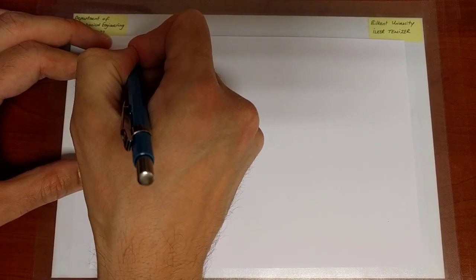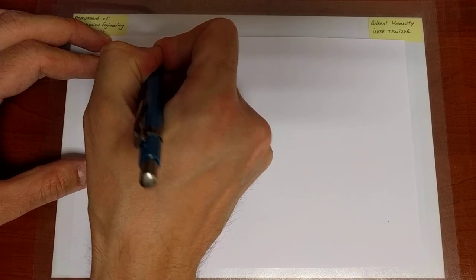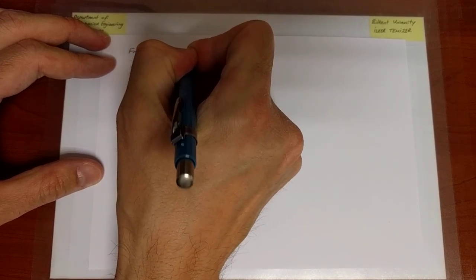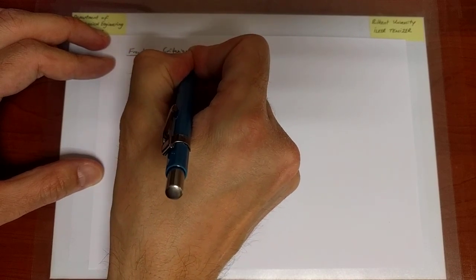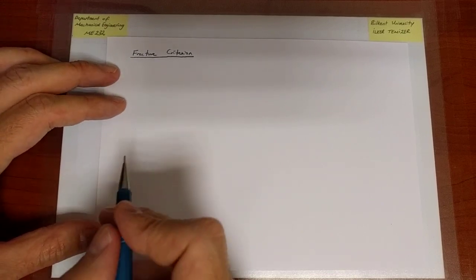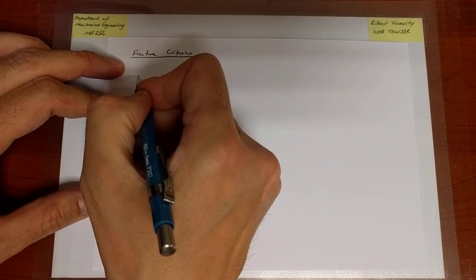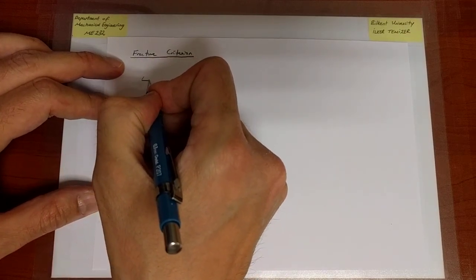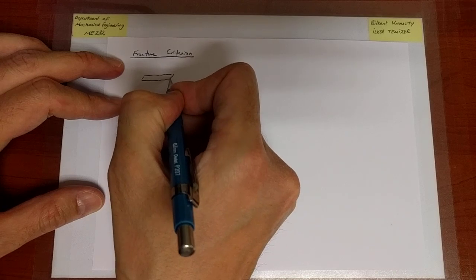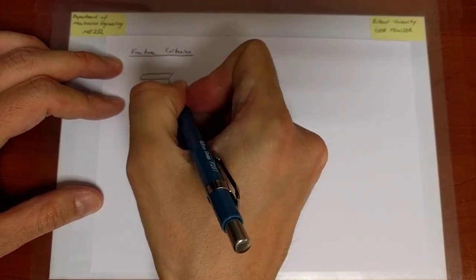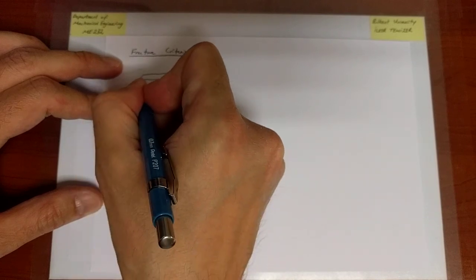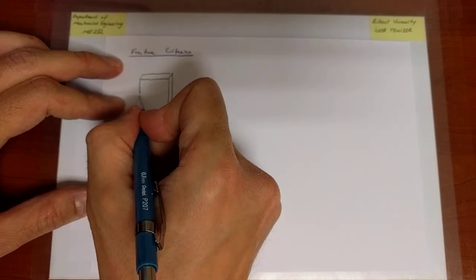So that simple experiment will help us formulate a fracture criterion. A criterion that ultimately helps us assess whether a structure with a crack will ultimately fail or not. And let me summarize the experiment that we have just carried out in a slightly different context, but ultimately the idea is the same. What we have presently is a plate, and this is not a perfect plate, but rather it has a crack on one side.